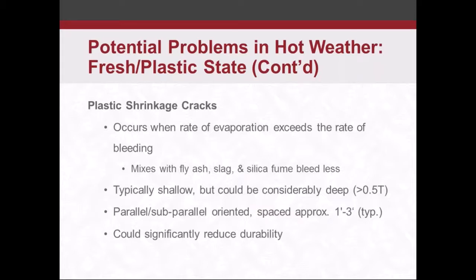So plastic shrinkage cracks are probably one of the most common problems that we see, and that occurs when the rate of evaporation exceeds the rate of bleeding. It's mostly an issue when you've got flat work, those slabs where you've got a large surface area exposed. Some mixes bleed a little bit more than others. Those mixes with fly ash, slag, or silica fume don't tend to bleed quite as much. But as the bleed water comes up to the surface, if that rate of evaporation exceeds the rate of bleeding to the surface, that top surface is going to dry out, and you could potentially get some shrinkage cracks.